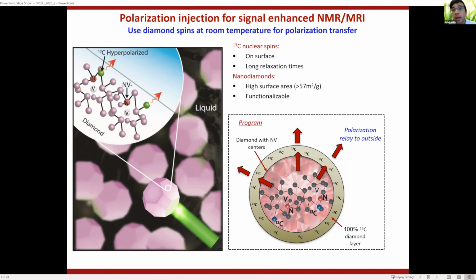the T1 to go down. But we actually grow, through CVD growth, overgrow pure C13 with no defects, to the extent possible. And it's really a question of how you can get epitaxial growth, and with a single crystal this is very much possible, to get pure lattice match. And then the idea is that we would transfer from carbon inside to carbon outside, but the carbon outside, which is in the shell, has very long T1 and very high density because it's enriched. And then we will try to use CP, cross polarization techniques, to go to the outside.